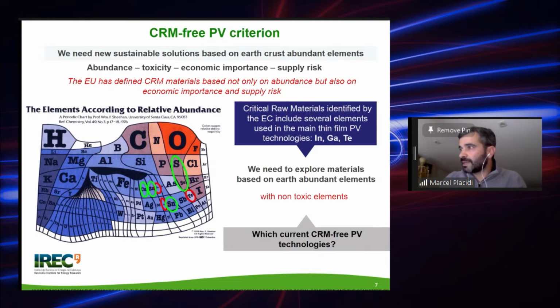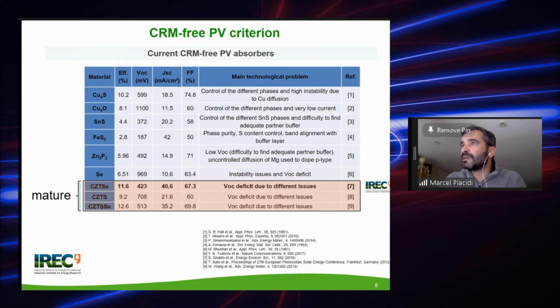So if we look at the literature, which are the current CRM-free, so critical raw material-free PV technologies, here we can see in this table the different materials we can find and which have been fabricated into solar cells. Some of them giving very good efficiency, such as copper sulfide, but we see that the best efficiency in all the cases is achieved with this family of materials, which are the kesterite. Kesterite is formed by copper, zinc, tin, and selenium or sulfide.